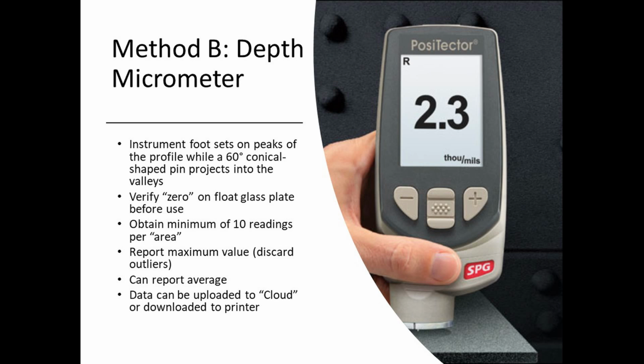What ASTM says, you're supposed to take 10 readings per area. It doesn't say how many areas. When you choose an area, you're supposed to take 10 readings. It sounds like a lot. You get about 10 readings in about 12 or 15 seconds with this gauge. You don't have to write them down. The gauge will memorize them for you. Remember I said we can speed up inspection by not having to record information as we're gathering it.